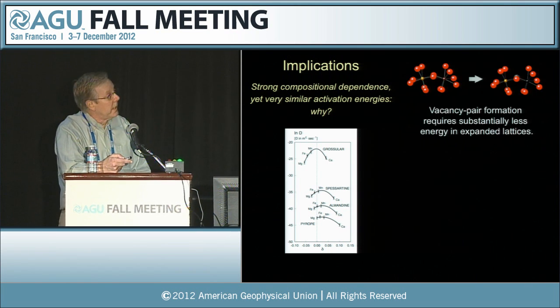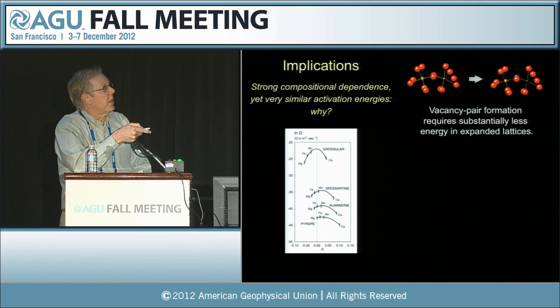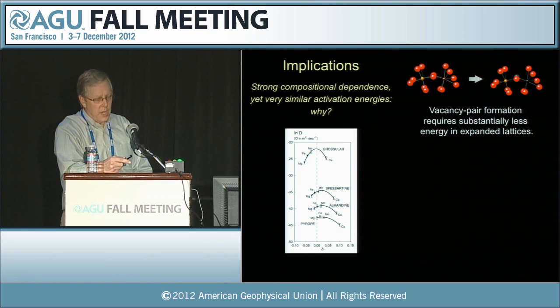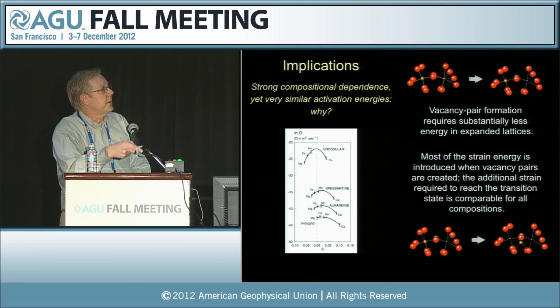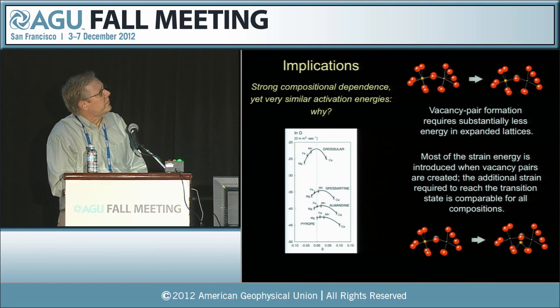Why should that be? Well, the answer is that this vacancy pair formation requires substantially less energy in these expanded lattices. So we have the ability to diffuse much more rapidly in those lattices. And the point is that that's the key factor. That's the main thing. Most of the strain energy is introduced when those vacancy pairs are created. The additional strain required to reach the transition state is small and is, in fact, comparable for all of these compositions. So that produces these very similar activation energies.